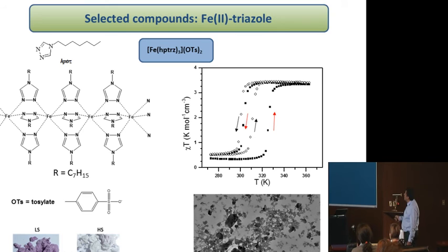So just an example, here you have a heptyl chain on the triazole, and the counter ion is a tosylate. For these complexes, we always perform 2 thermal cycles to check the effect when you remove the solvent at high temperature. The first cycle is with solvent, and the second one is without solvent. Again, for the complex without solvent, we have a spin crossover at room temperature with a hysteresis.